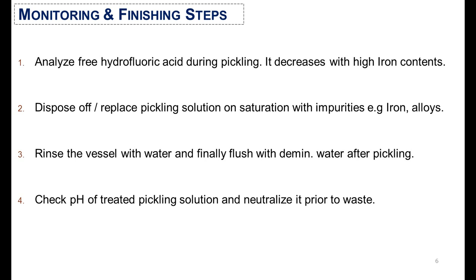There are some steps which need to be monitored during this treatment. First, analyze free hydrofluoric acid during pickling, because the free acid content decreases with high iron content. Second, dispose of and replace the pickling solution when it becomes saturated with impurities like iron and alloys. Third, rinse the vessel with water and finally flush with demineralized water after pickling. Fourth, check the pH of the treated pickling solution and neutralize it prior to waste.